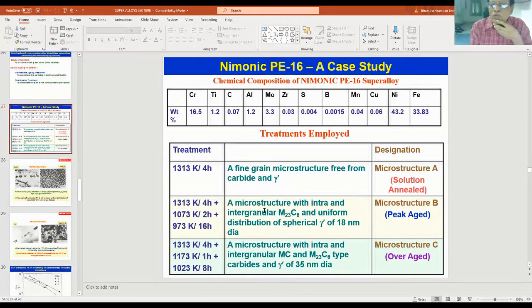For the treatment employed for this superalloy, you can see the solution treatment at 1040 degrees centigrade. If you go to higher temperatures, above 1040, grain coarsening will occur. But for fatigue resistance, a fine grain microstructure is required, which is free from carbide and gamma prime. So 1040 degrees centigrade is enough to cause all the earlier precipitated carbides and gamma prime to go into solution. So I call this microstructure A, in the solution annealed condition.